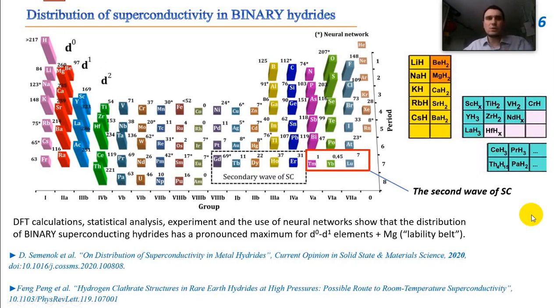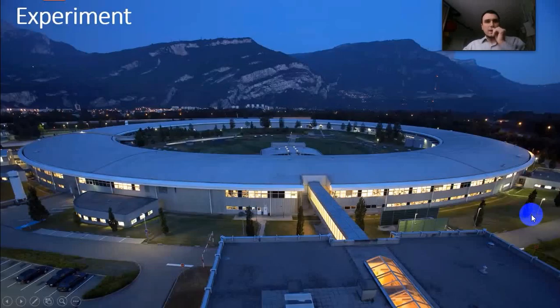So that excludes superconductivity, and all high temperature superconductors among polyhydrides are located exactly in this superconducting belt among d0, d1, and d2 elements. It's interesting to note that this belt exactly coincides with the maximum of hydrogen content among the lower hydrides, which can be synthesized at normal conditions, at atmospheric pressure. And it's very interesting because we can extrapolate the data obtained at low pressure to the region of high pressures. Okay, let me say now a couple of words about experiments.